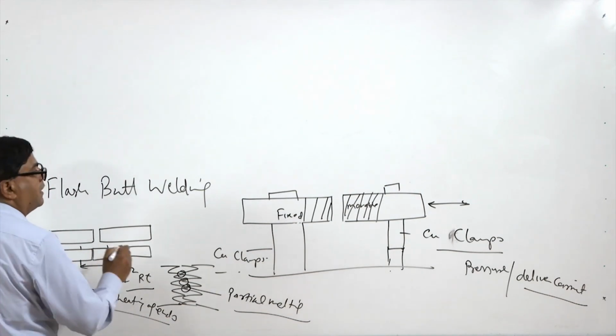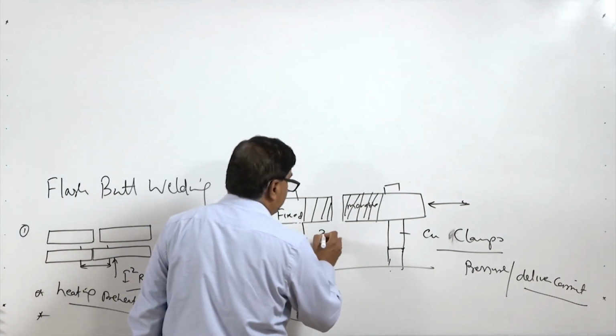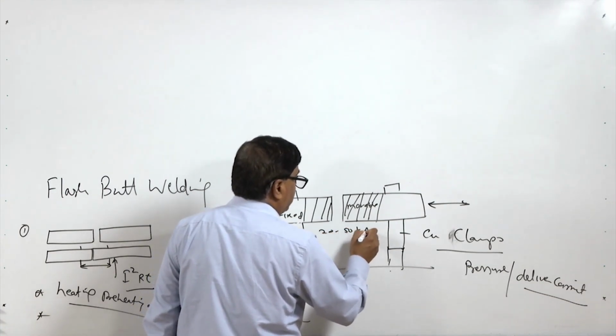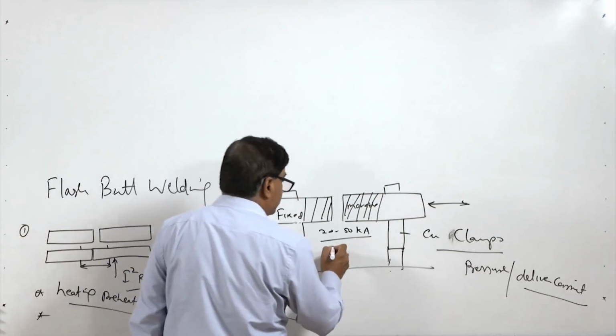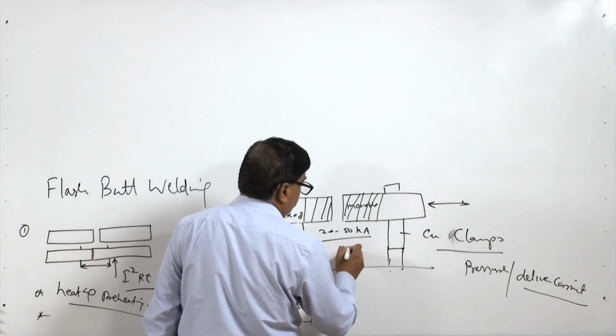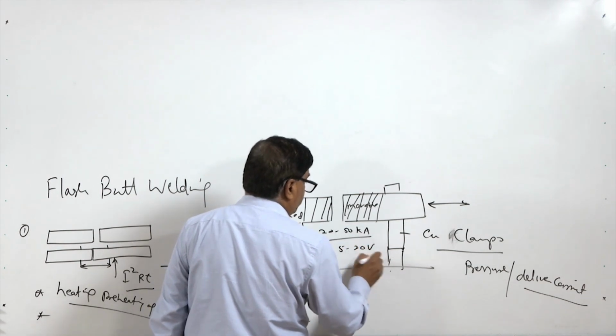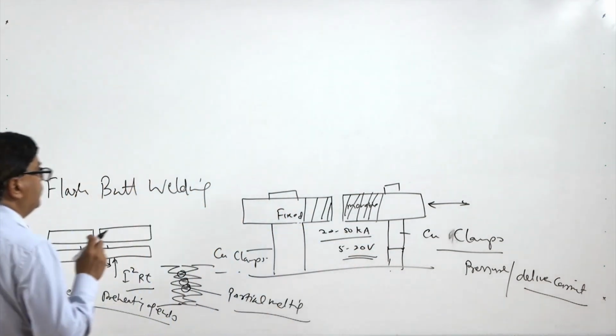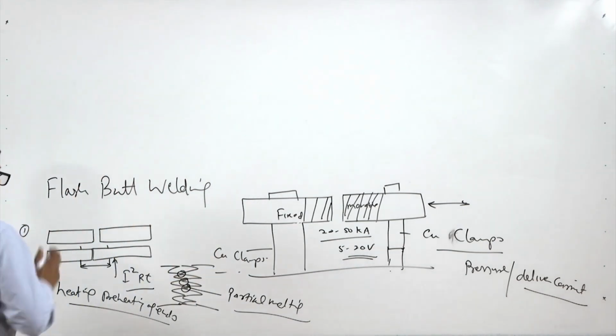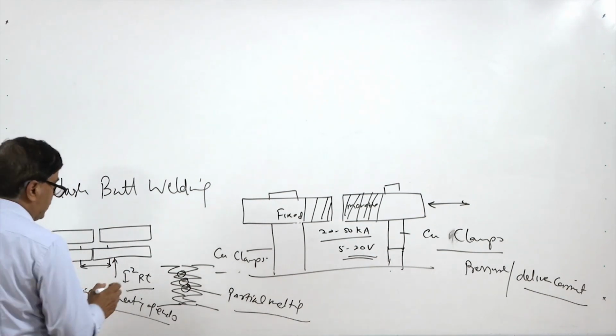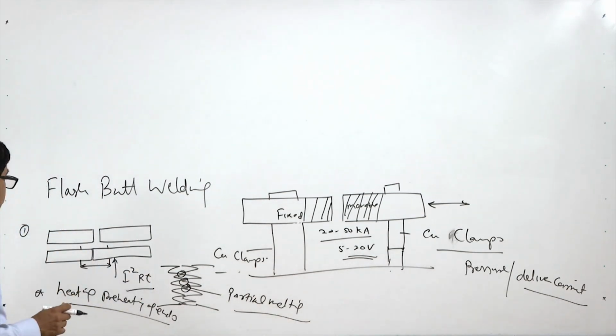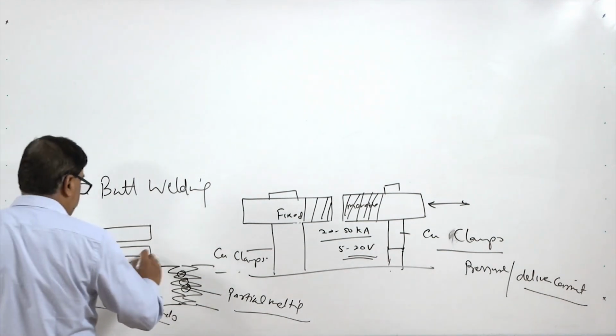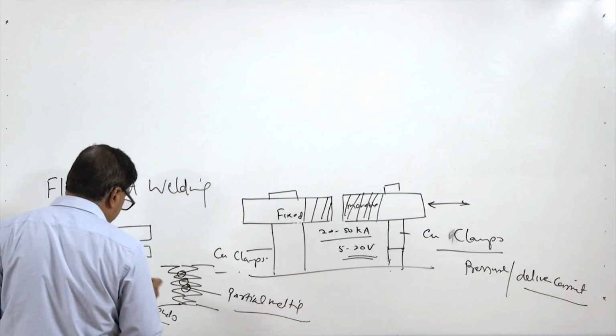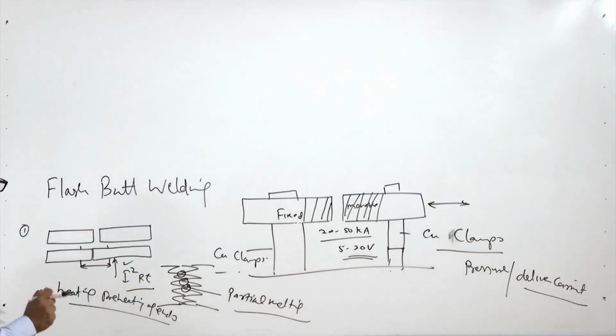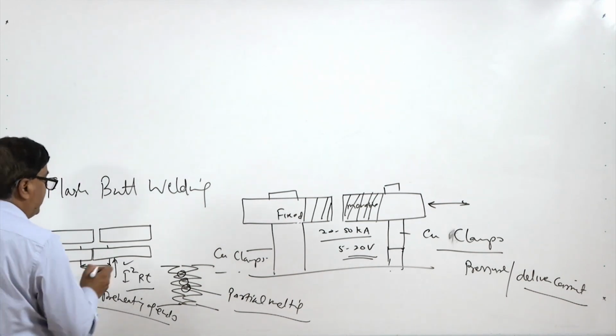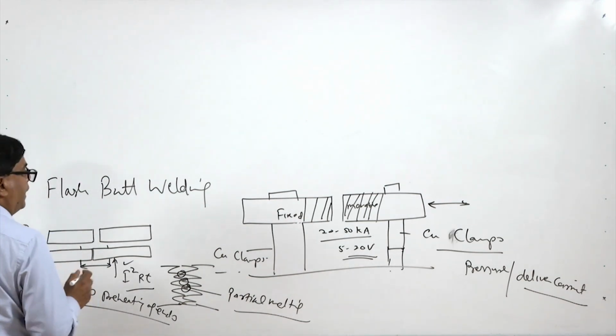In addition to this, the flow of the current is very high. The current which is allowed to flow may be say 20,000 to 50,000 ampere, and the voltage is quite low, maybe 5 to 20 volts. So, very low voltage and very high current is allowed to flow through the workpieces. Since the section size is large, the resistance is limited, so to have enough heat generation the current has to be very high, and it is allowed to flow for some time. So, through I square R heating, preheating can take place, and then the movable component is moved apart.